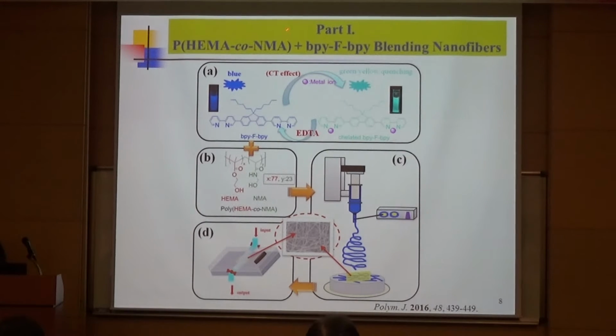So in the first part, we simply blend a random polymer, poly(HEMA-co-NMA), with fluorescent sensing fluorene-bipyridine compound to prepare the blending nanofiber. This fluorescent sensing compound is composed of fluorescent moiety and the two bipyridine metal ion chelating moieties. After binding with metal ion, the change in charge transfer effect will result in difference or shift in the fluorescent characteristic, such as color change or fluorescence quenching. This random copolymer is composed of hydrophilic moieties HEMA for good swelling of water in aqueous solution, and also the thermally cross-linkable NMA moieties for retaining the fibrous conformation in aqueous solution. So we use the blending solution of copolymer and the sensing compound for electrospinning to prepare the blending nanofibers.